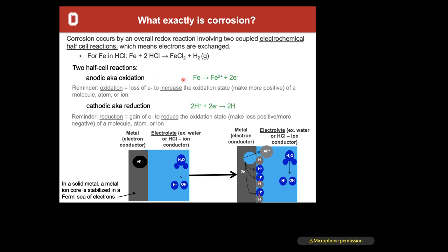And when it does that, the metal atom will become an ion. And it can't still be an ion in the metal state, right? So it's going to come out. We're actually physically losing an atom from the material itself, and it's becoming an ion freely floating in my electrolyte. So, a little diagram down here, this is now for aluminum and water. I have my metal. We think of it as a sea of metal ions, and all of the electrons in the valence state can flow freely around it. And here is my aluminum atom sitting here. It has its valence state so that you can see what it's going to become, right?